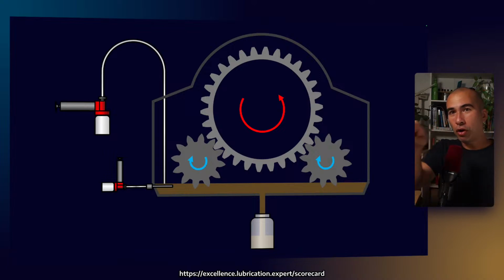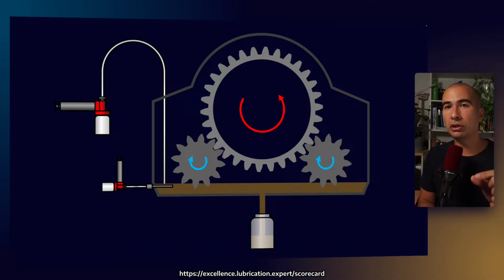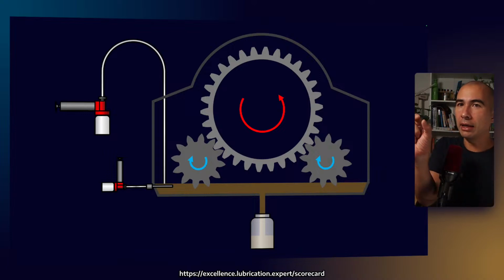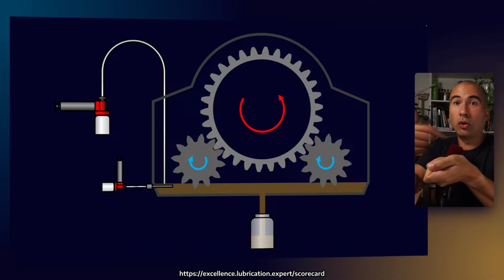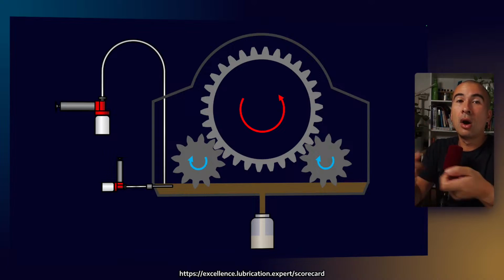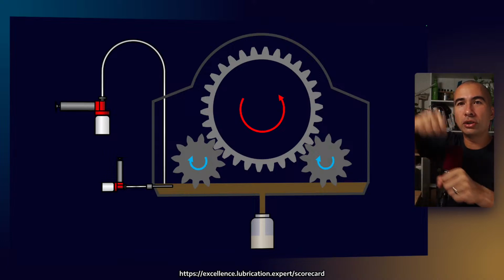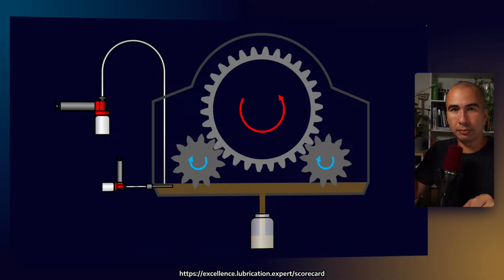So we have a probe that goes into what we call the live sampling zone, an area where we have turbulent flow. Depending on whether our system is pressurized or non-pressurized, we might have something called a minimess, which is basically a one-way valve. If the system is pressurized, we can simply push on that one-way valve and oil will come into our sample bottle. Or alternatively, we can use a vacuum sampler to draw a sample.